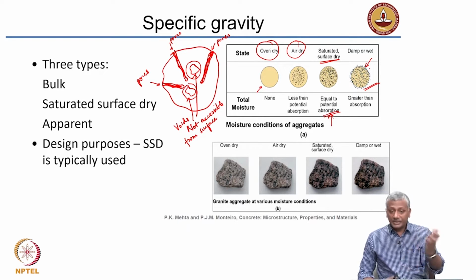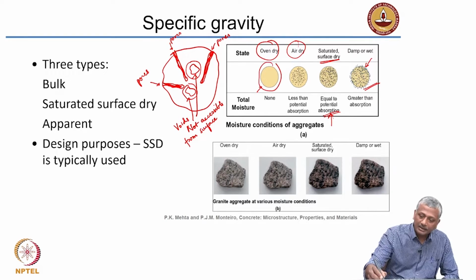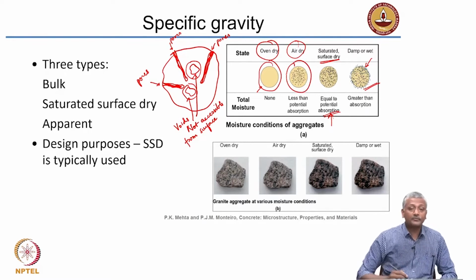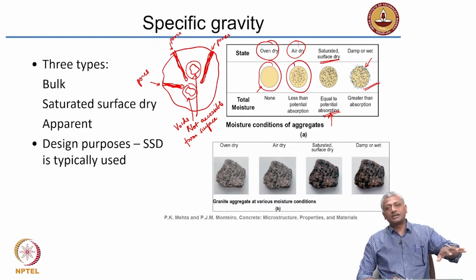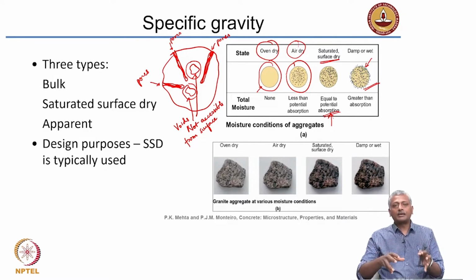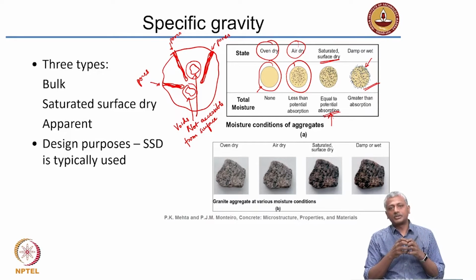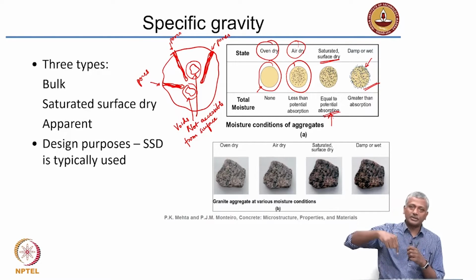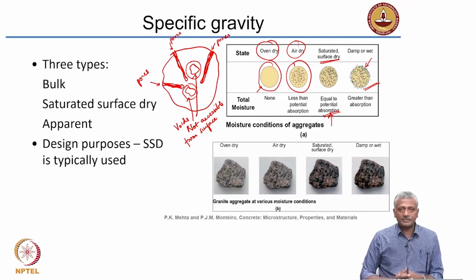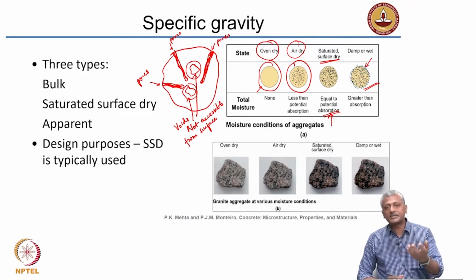On the other hand, if the aggregate is dry like this, or air dry or oven dry, which has a lower moisture content than the limit that can be absorbed, when you put this aggregate into concrete, it will start absorbing moisture from the water that you wanted to put in for the mix in the first place. So, it is absorbing moisture. That means you need to put excess water to compensate for this absorption. That is why in concrete mix design, finding out the moisture state of the aggregate is very important.